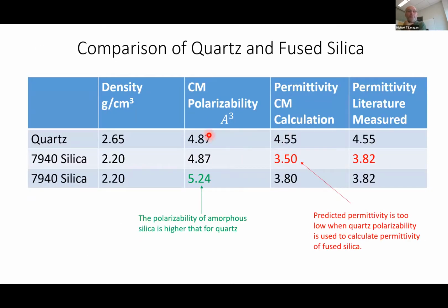We can see here from that polarizability from that table I just showed you that we would calculate a permittivity value of 4.55. And indeed, if we look at literature, this is the case. If we take that same polarizability value for fused silica or the amorphous material, we underpredict the permittivity. As we see, the measured value is 3.8, but here the predicted value is 3.5.